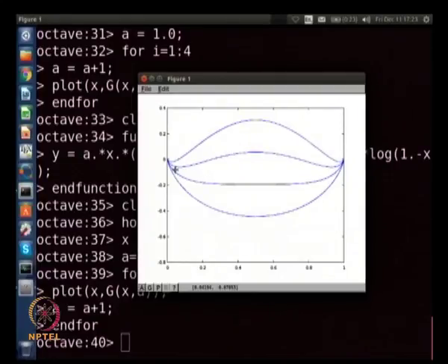You remember, if you go to very low temperature, the phase diagram boundaries are closer to the end compositions. As you come to higher and higher temperatures, the phase diagram is like a parabola, somewhere about 0.5 is where its top point is. So, as you go to higher and higher temperature, these points come closer and closer together, and at some point they merge and the 0.5 becomes a point at which they have the same value. Above that, the curve becomes the same as the entropy curve, which means there is no longer any two phase region.